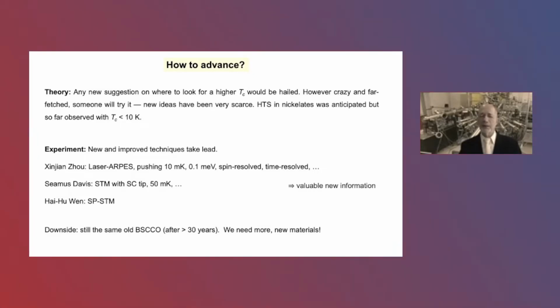On the experimental side, I think first and foremost, we need to push the technique further. And there were at this conference several beautiful examples. Xingjiang Zhou showed spectacular advances in laser-based ARPES, pushing the resolution from 5 millielectron volts down to less than a millielectron volt, perhaps 0.1 millielectron volt, and then measuring at 10 millikelvin dilution temperature, with spin resolve, time resolve, and so on. Seamus Davis showed STM with a superconducting tip operating in a dilution fridge, and Hai-Hu Wen just some hour ago showed spin polarized STM measurements.